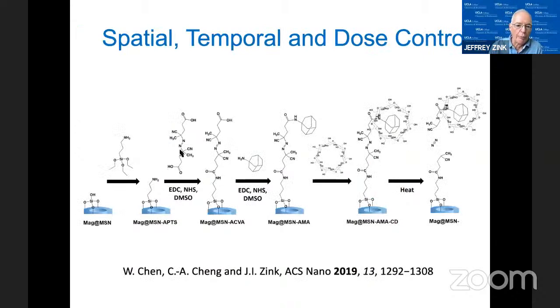And finally, the one we've been using mostly now, again, involves this azo type group in the center here, where the bond thermally breaks it. And here is another snapshot. We just attach a big bulky system, as shown in the overall right there, onto the system. When that bond breaks on the very far right, then that big bulky cap just breaks off, and we can release the drug. And this is our most active one right now.